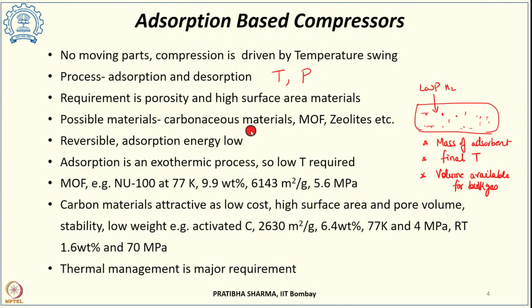Different materials have shown very promising adsorption capacities. Carbon based materials — such as carbon nanotubes, activated carbon, or fullerenes — as well as metal organic frameworks, zeolites, and similar high surface area materials with very high adsorption capacity are used. The adsorption-desorption process is completely reversible, with interaction energy of 0.01 to 0.1 electron volt. This is also an exothermic reaction, so it is preferred at low temperature.